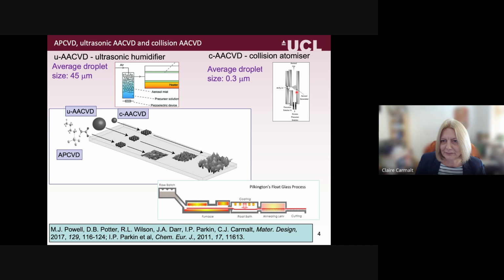If you change the way you create the aerosol to something known as a collision atomizer, which produces the aerosol droplets under higher pressure, you tend to form much smaller droplet sizes, and then you can end up with even greater textured morphology. So that can be quite important depending on your property. Most of the ones we do use the ultrasonic, just because it's much easier to set up and use for the students and so on, but we have done quite a lot with collision as well.